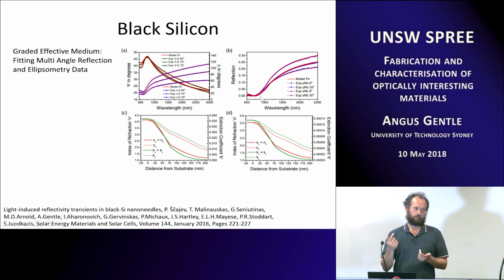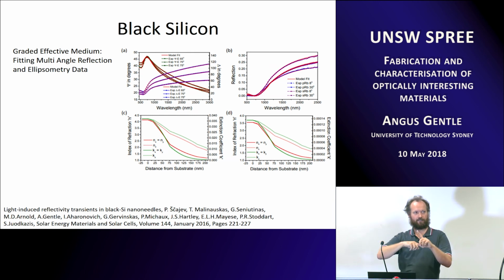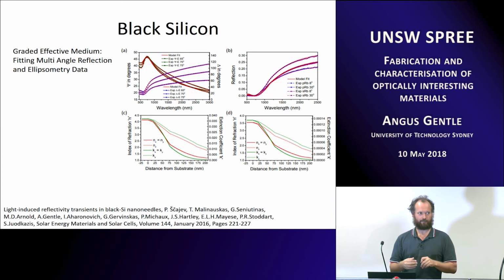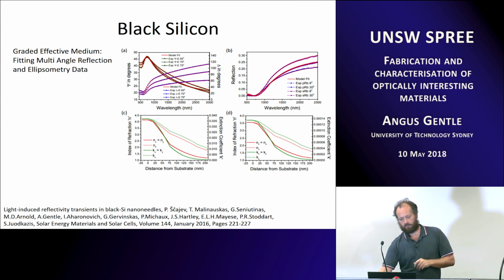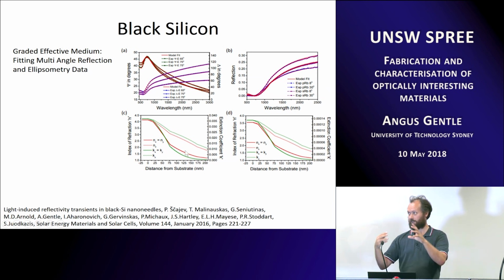And so got sent some samples and then went, this measurement won't take too long. It took a very long time to measure it and then try and fit it. So the hard thing with ellipsometry is fitting the data. If you've got black silicon, you've got these nice tapered things, which are some length. Hopefully the people have done TEM for you and they give you the shape and size. Usually that's not going to be the case and it's not going to be right anyway, so you end up trying to fit it. Eventually came up with the model which matched. We ended up redoing SEM on the exact sample we had and then saw that it was this shape.